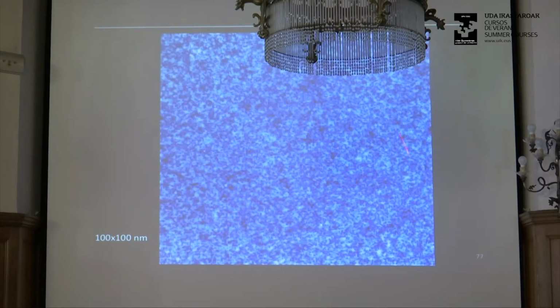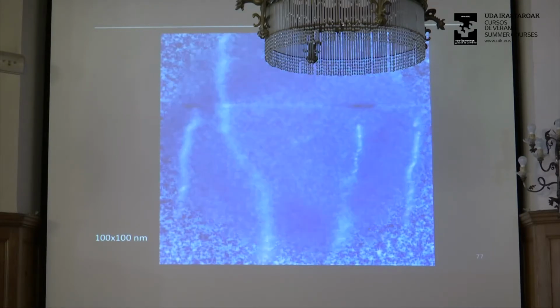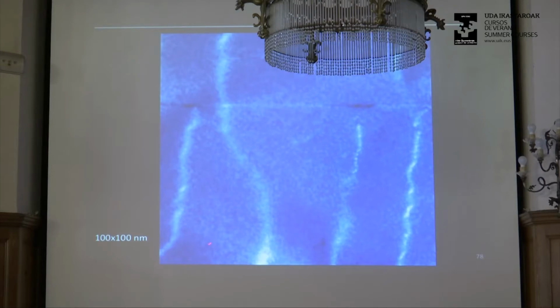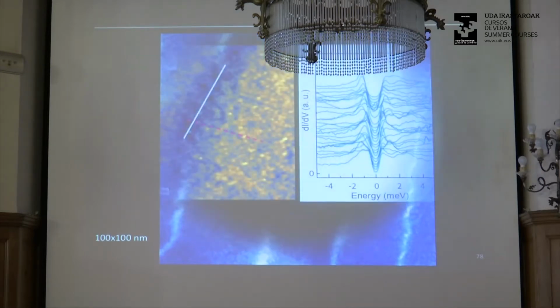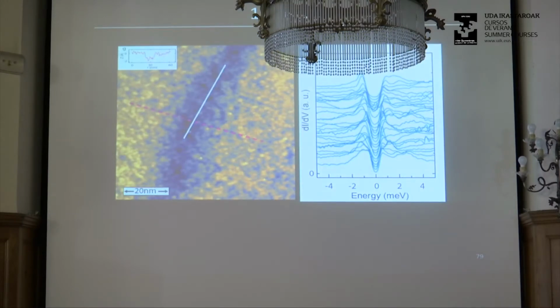So here's our beautiful sample, FeSeTe, no domain walls in sight, right? So I don't know how many of you have done STM. The beauty of STM is you can walk around and try to find things. So we did that. And if you go to another area, you can find areas with lots of domain walls like this, right? And in fact, sometimes you have to select samples with domain walls. So let's say you can do that and find domain walls. So here's one domain wall, right? It's this dark line here.